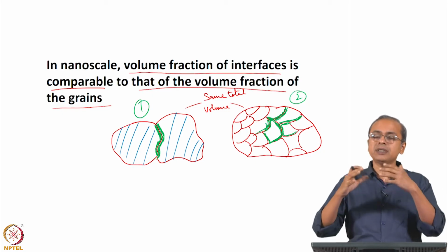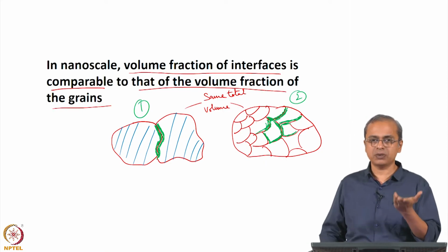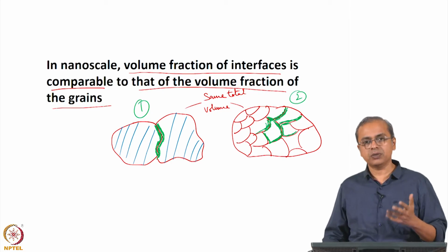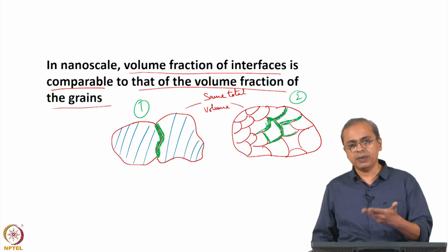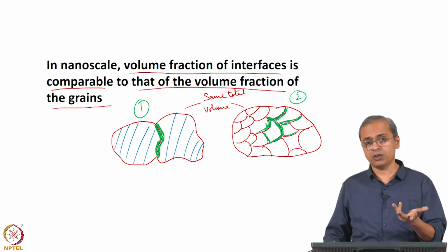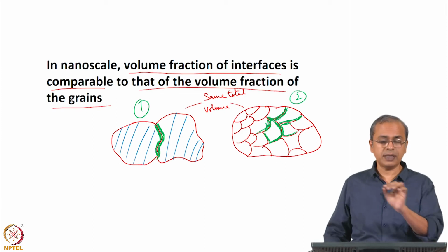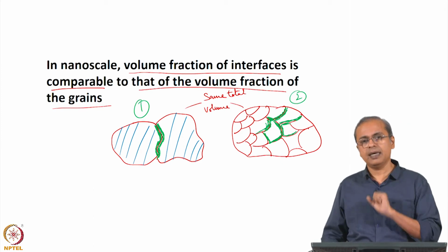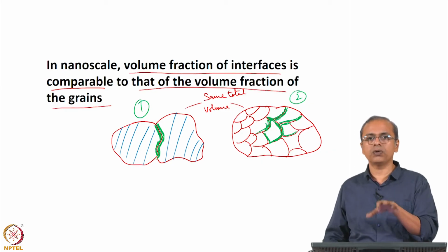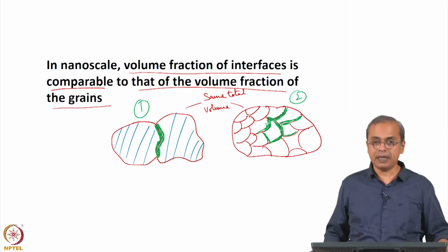And if you continue this into the nanoscale, the distance between atoms is only about 2 angstroms, so if you take 1 nanometer you have only 5 atoms, and if you take 10 nanometers you have only 50 atoms. Once you have crystals which are only about 50 nanometers across, then even if you assume 3-4 angstroms across the interface as being related to the interface, you already have a significant fraction of the total volume associated with the interfaces. So they start becoming comparable.